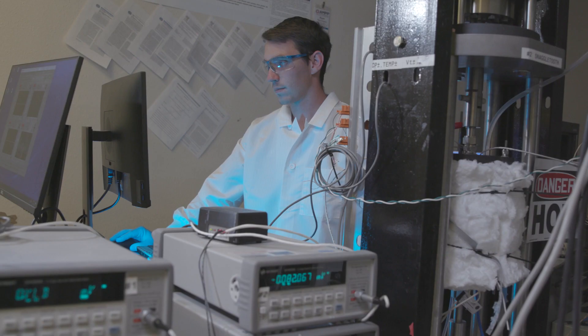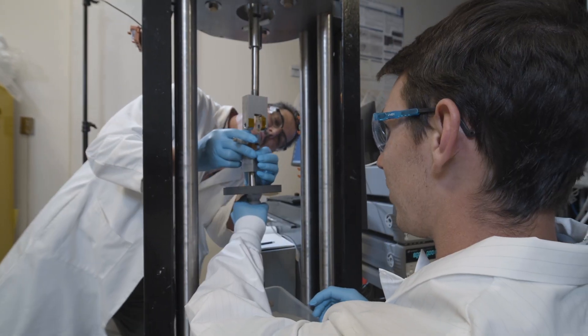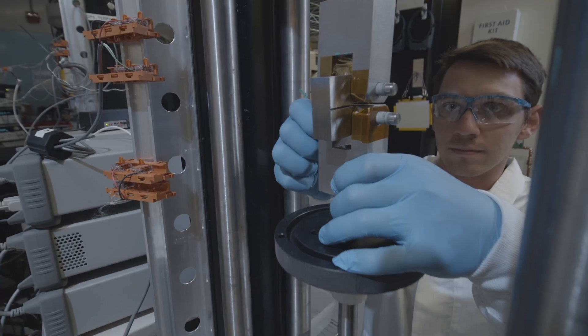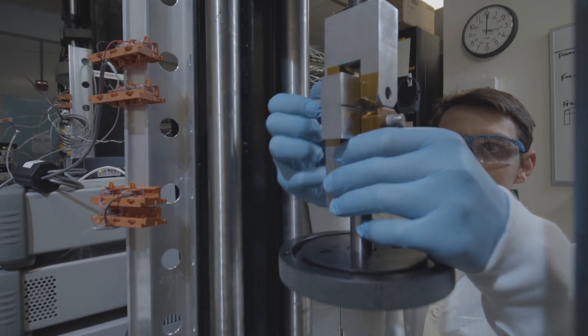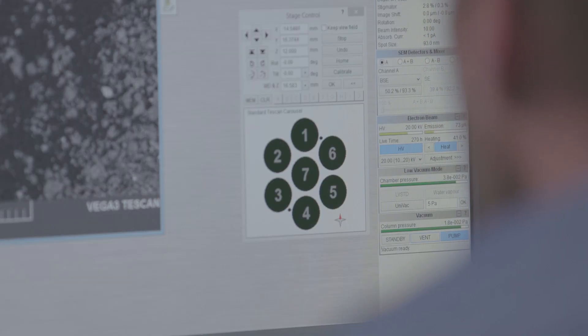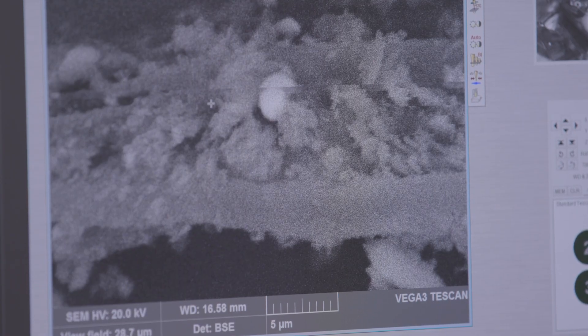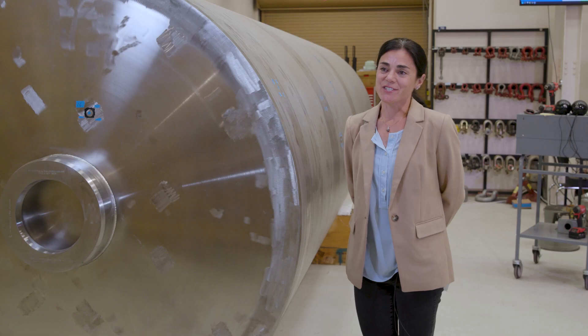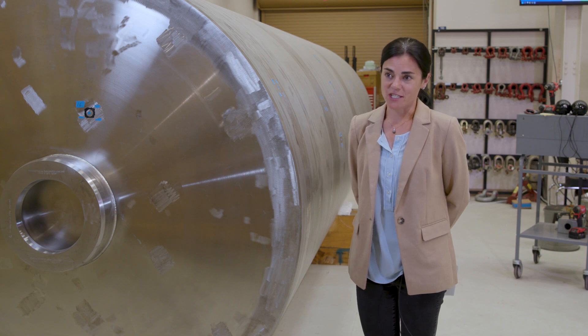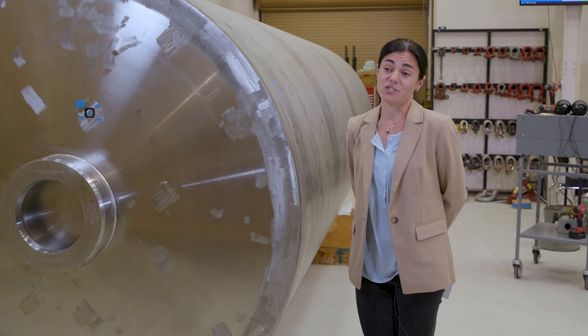We apply both electrochemical testing and large-scale atmospheric exposures to compare and validate maximum pit size models. We study U-bend exposures under various atmospheric conditions to explore influences of material and environment on the pit-to-crack transition. We measure crack growth rates on canister materials under relevant environmental conditions to determine crack growth rate dependencies on material and environment. The combination of environmental characterization and corrosion studies helps us to better understand and predict the occurrence of potential stress corrosion cracking, informing both maintenance and operation strategies as well as potential mitigation and repair options. Sandia's research and development combines both the geographic spatial location and the canister surface location to develop a better understanding of the potential occurrence and timing for stress corrosion cracking.